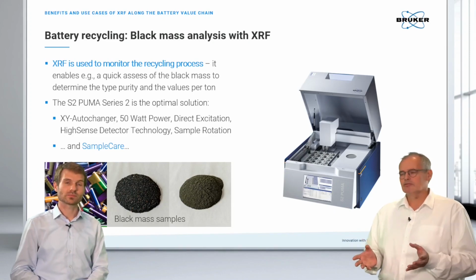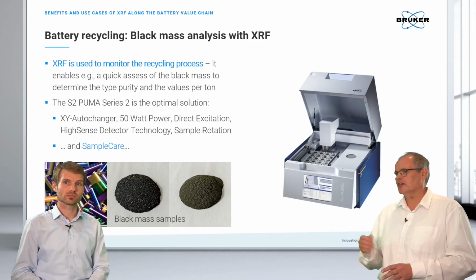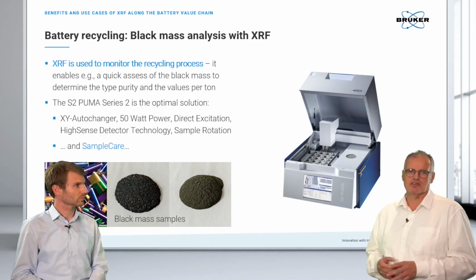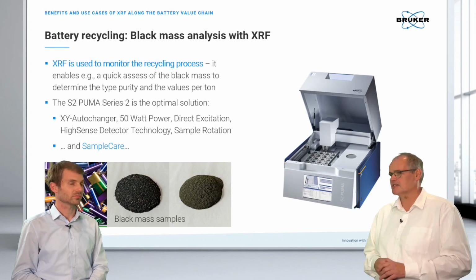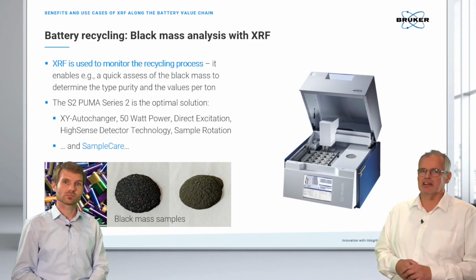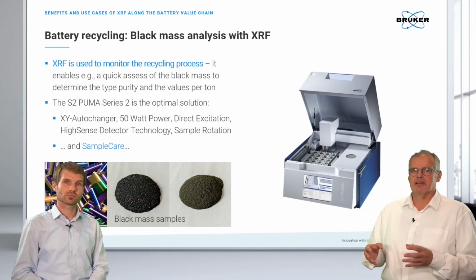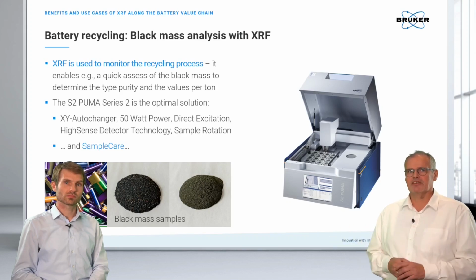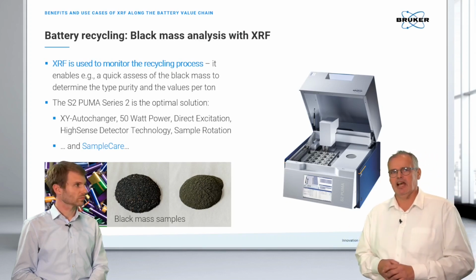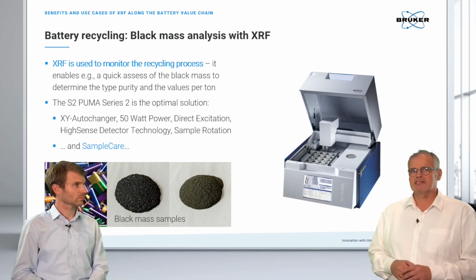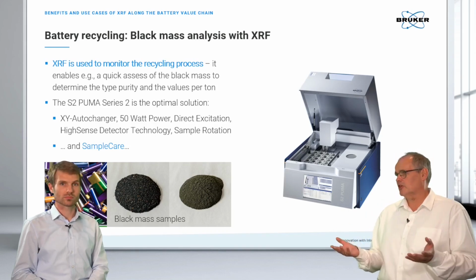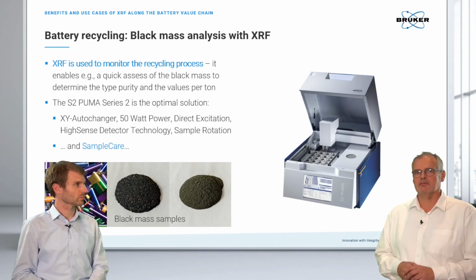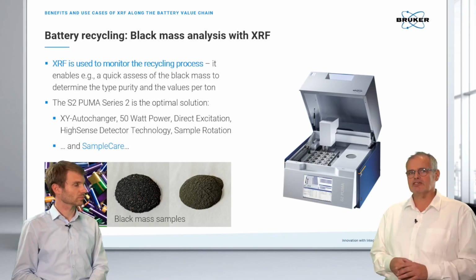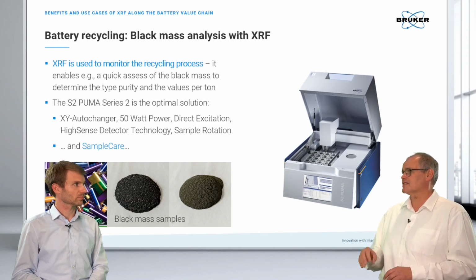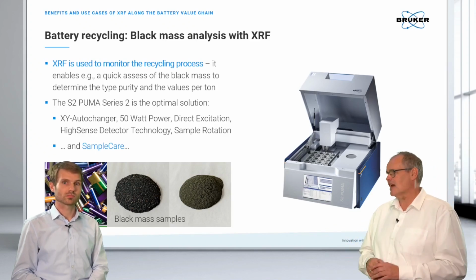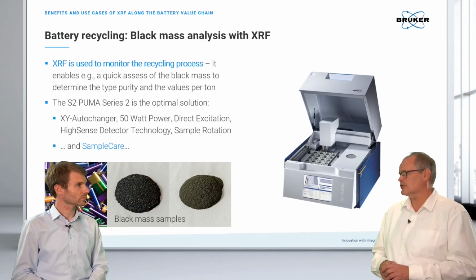Yeah, we receive this material and we want to determine the commercial value, especially how much cobalt, manganese and nickel is inside. The benchtop XRF instruments are very ideal. The S2 Puma has enough excitation power to determine all the necessary elements on the one hand. On the other hand, it also has some precautions, because we learned these are pretty nasty samples and there must be some precautions in the instrument.